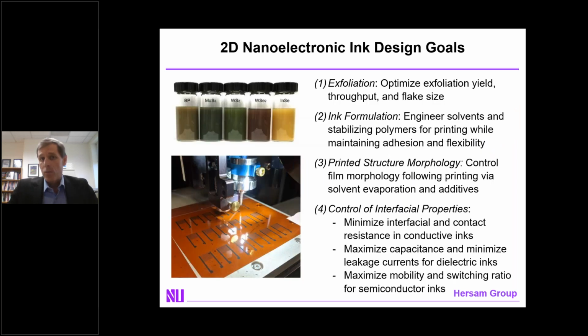To achieve this goal, we have to break it down into multiple sub-goals. The first is exfoliation. Typically, we're going to be peeling away or exfoliating these 2D materials from bulk van der Waals solids. We need to do that in a way that optimizes the yield, throughput, and flake size. We then have to formulate the inks, which will require engineering the solvents and possibly also stabilizing polymers to enable effective printing while also achieving adhesion and mechanical flexibility.